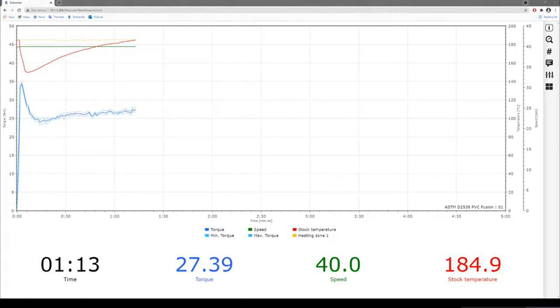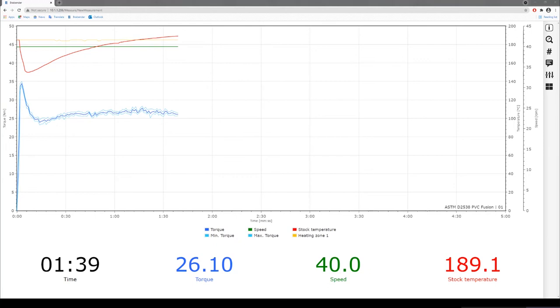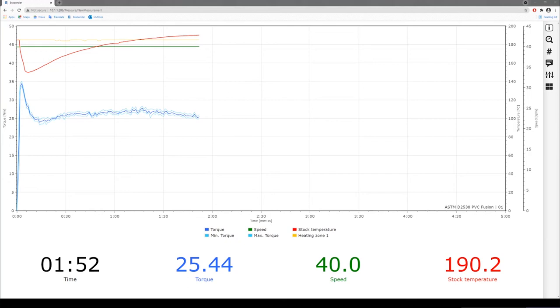You can see we had like 35 newton meters of loading peak, then it was dropping down to 25 newton meters, then it was crawling up to a secondary peak which is a little bit prolonged. Then we will see that it will fall down to a more stable phase. The red curve is the temperature, I have the speed of 40 rpm, and this is currently what the readout is, what is most likely always used in the industry as a quality control or formulation development tool for the mixer.